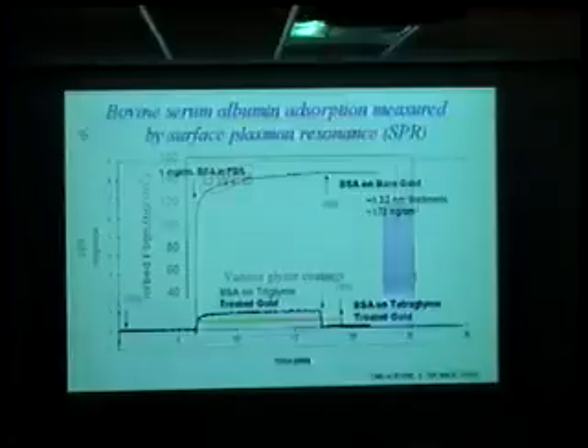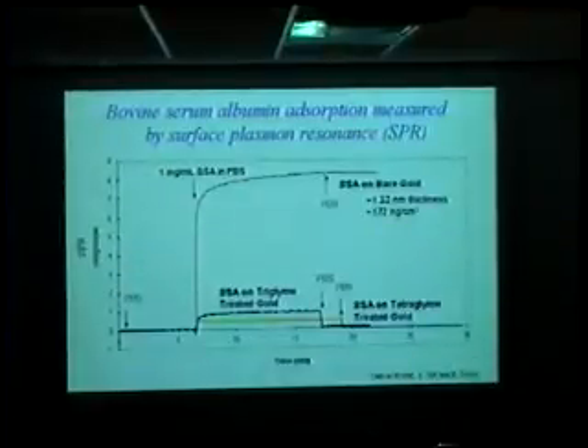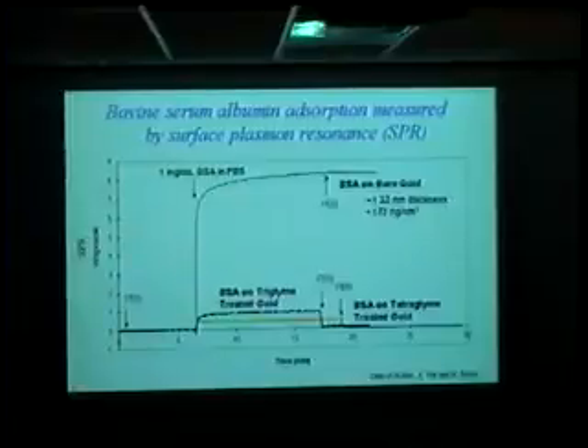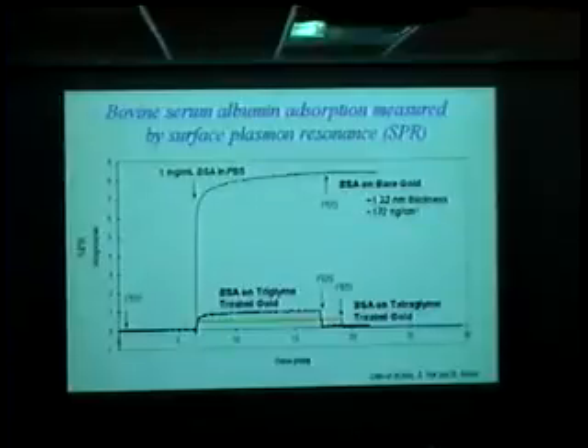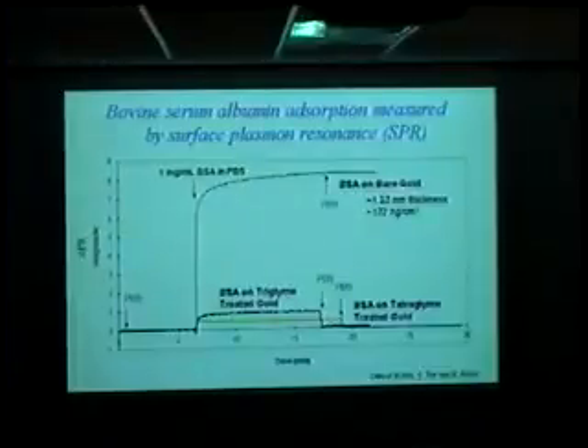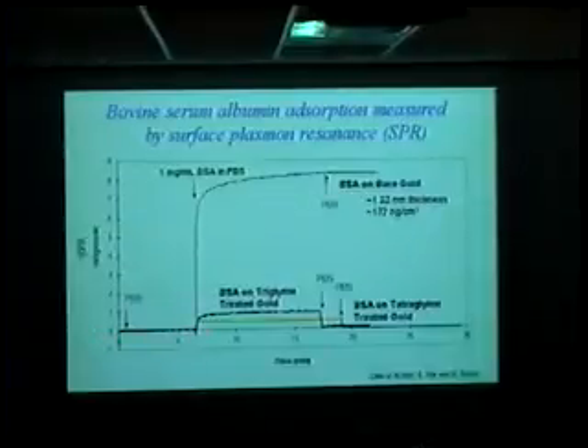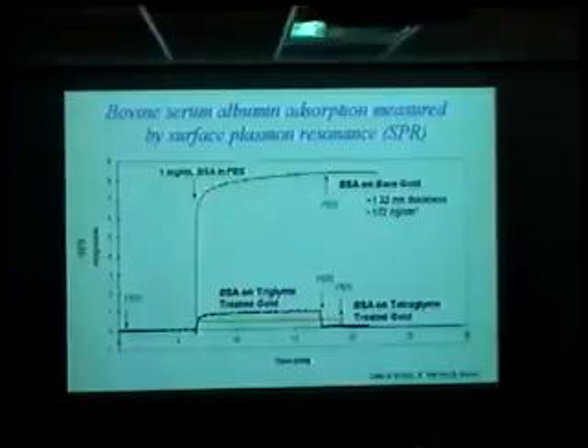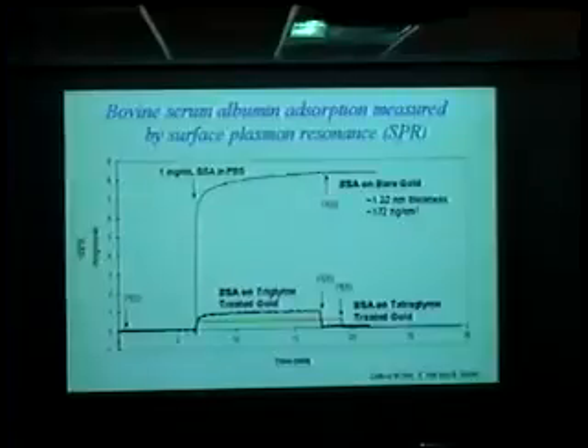We can't measure any pickup. That's good. We really learned how non-fouling these are using a technology called surface plasmon resonance. What this methodology does is measure a change in refractive index at a surface with great accuracy. So if our surface is bare gold and we start adding some buffer, which is a function of time, we're going to add some buffer. And as soon as we add some bovine serum albumin, we see a huge change in the surface refractive index. It plateaus as we reach a monolayer of albumin on the surface. And then we add a buffer stream again and try and wash it off. And we can't. It's irreversibly adsorbed.